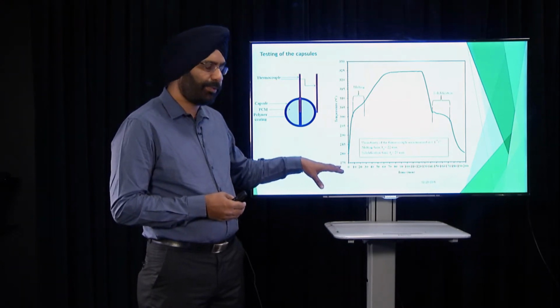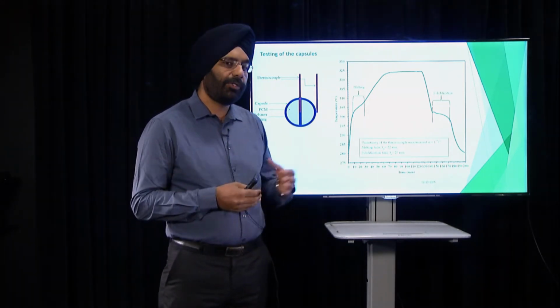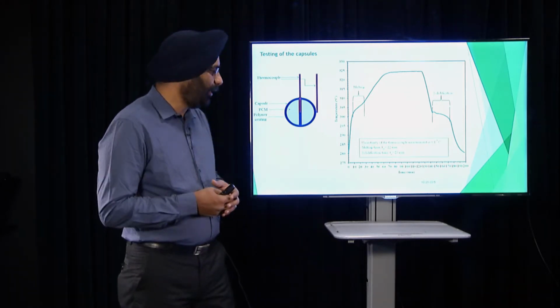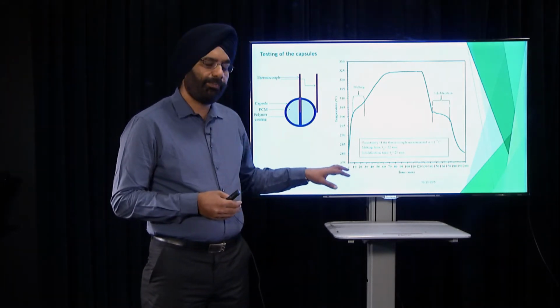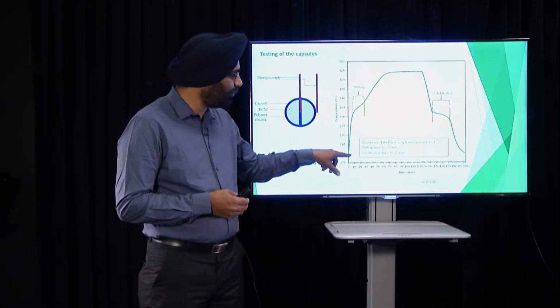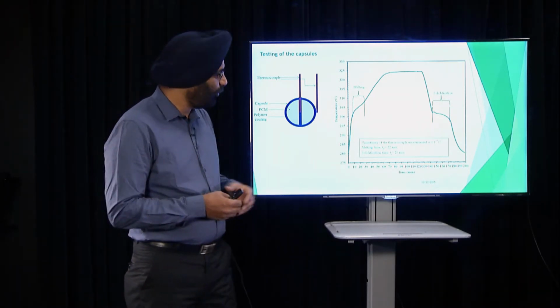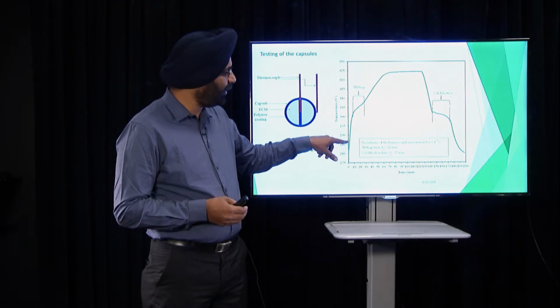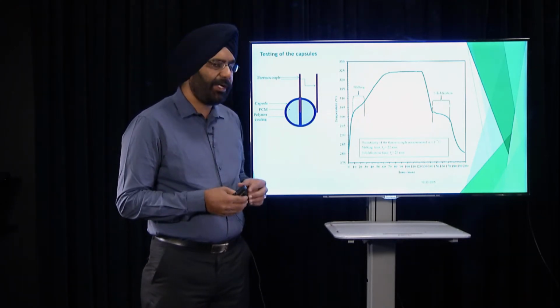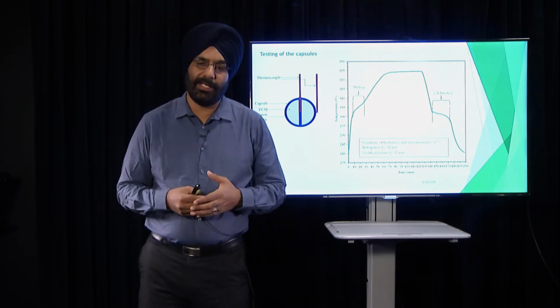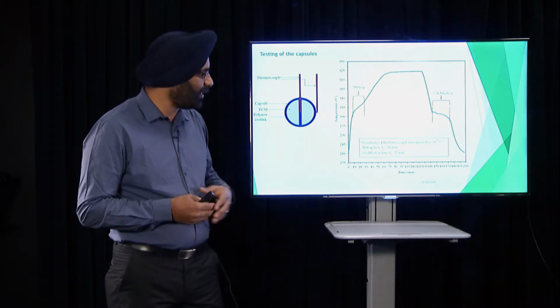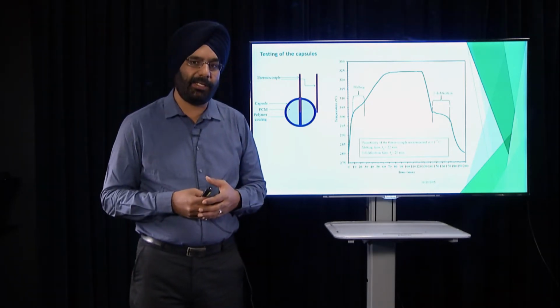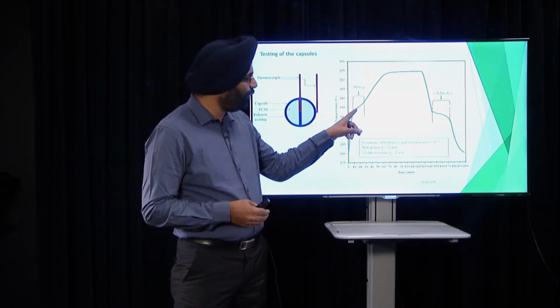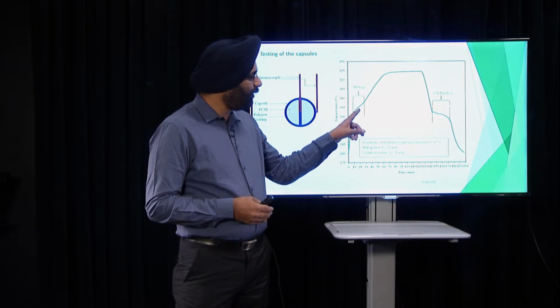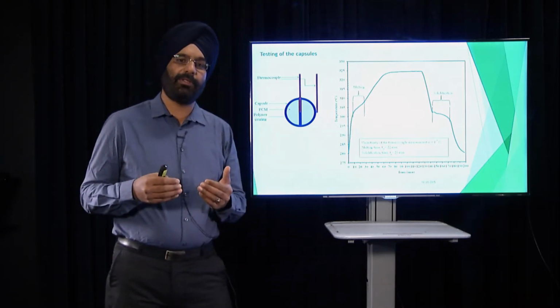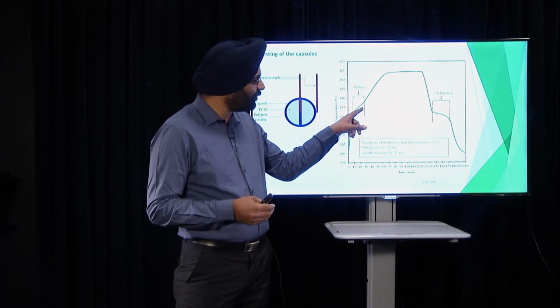So starting from room temperature to the temperature 20 degrees above its melting point. Now in this graph we didn't show the room temperature, but it's shown from 280 degrees C. So what you see is, as you start heating it up, the rate of increase in temperature is very, very fast. So it increases very fast there. But there comes a point where the rate of increase in temperature becomes slow. It's almost like a flat structure in there.